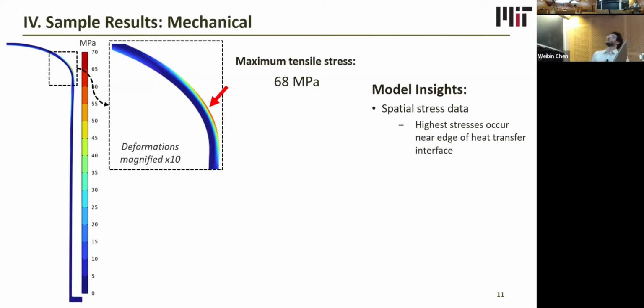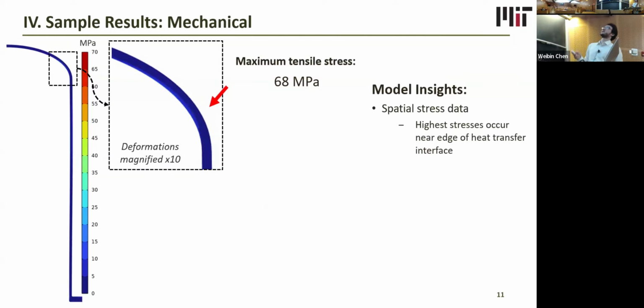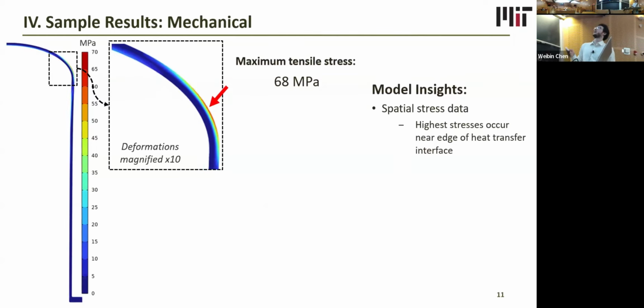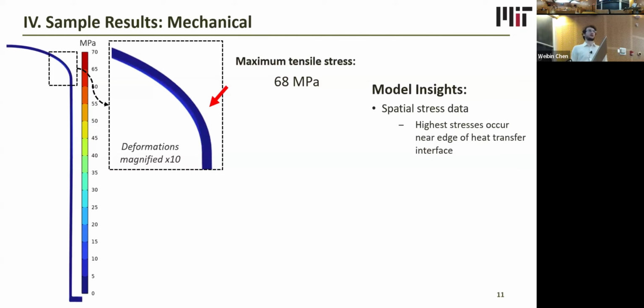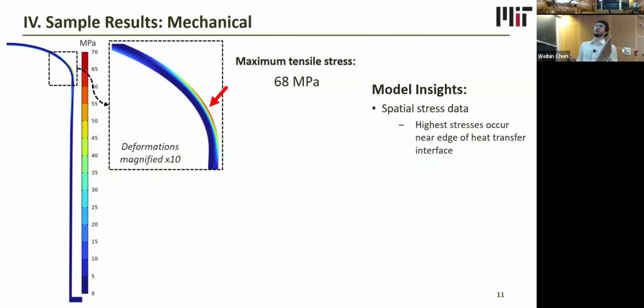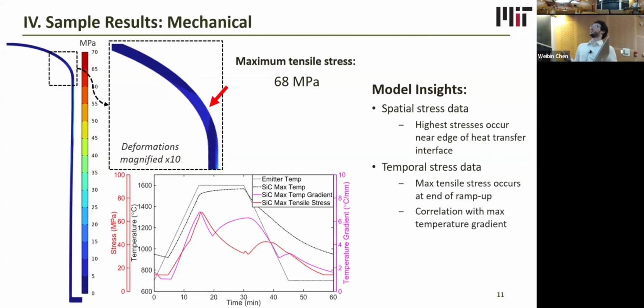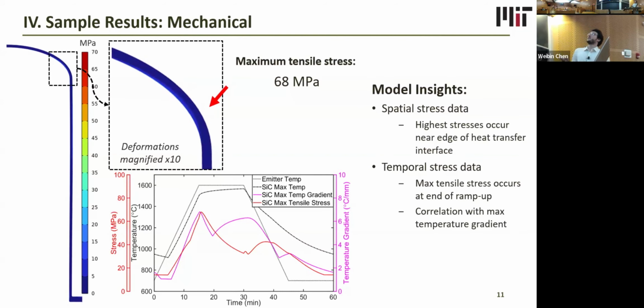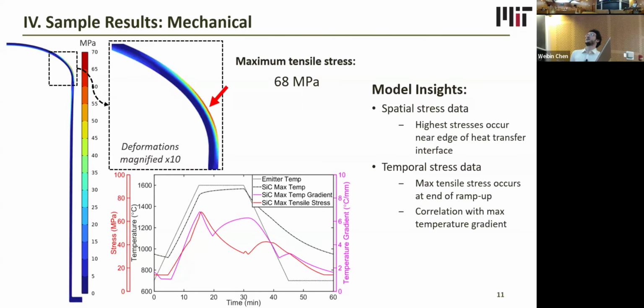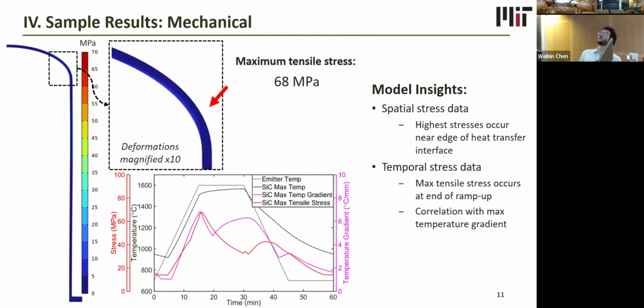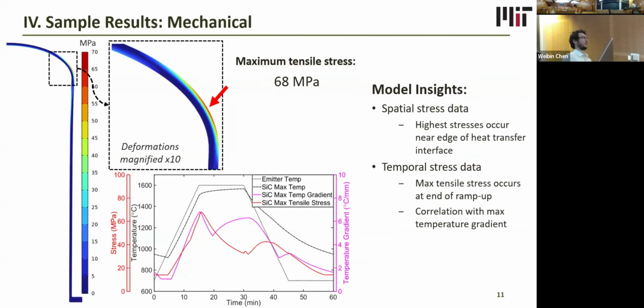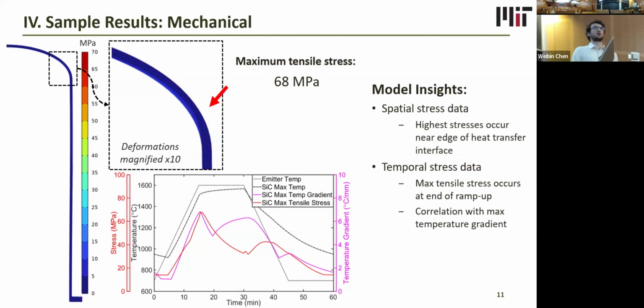So here's some sample mechanical results. We can see here the tensile stress field over an entire cycle, and in this inlet is the area where the maximum tensile stress occurs on the outside, 68 megapascals. This spatial data is very important for our modeling, as it shows where we need to focus on to improve mechanical stability. In this plot, we can see in red the silicon carbide maximum tensile stress, and in magenta, the silicon carbide maximum temperature gradient. And what we see is a very strong correlation between the two at their peak. So this temporal data can also show us when the maximums are occurring and what we need to focus on if we want to reduce stresses.